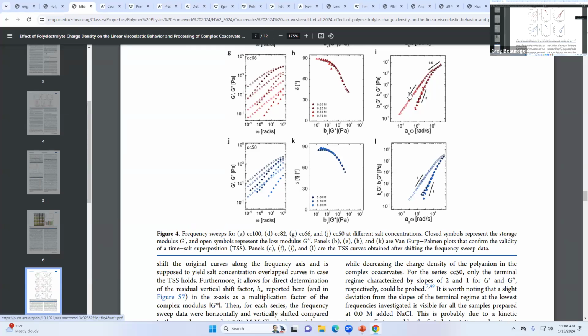So one of the main things he's talking about at the beginning, he says, all right, if you can shift them like that, that means that the mechanism that's involved is the same. In other words, for the simplest case of viscosity, you have a bunch of spheres and you move another sphere through them. So the spheres have to move out of the way. There's a simple energy of doing that. And when it does that, maybe there's an entropy involved. The organization has changed. And then also, if the thing has a glass transition where everything gets stuck, well, that's the endpoint. So you have to put that in.